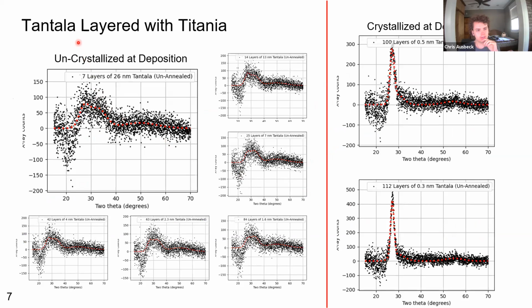Moving on to tantala layered with titania. So we have a very similar case with tantala layered with titania as we did with tantala layered with silica, but a bit different. So the 6 thickest samples, starting from 7 layers of 26 nanometer tantala, all the way down to 84 layers of 1.6 nanometer tantala, those were all uncrystallized when we first got them. You can see very similar amorphous peaks as the ones in tantala silica, all the way down to here.